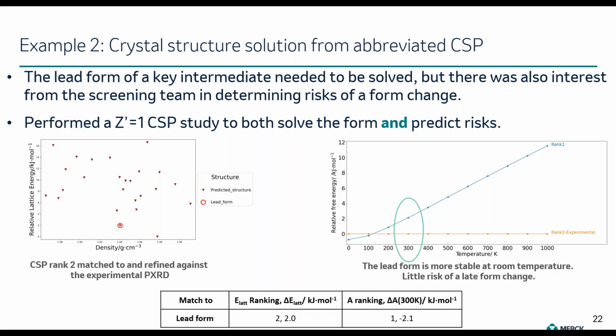And as you can see here, the stability changed quite drastically from lattice energy to free energy at room temperature. This crystal structure went from being metastable by 2 kilojoules per mole to be more stable than the lattice energy global minimum by approximately the same amount. And this is a very nice example of how in the same study, we were able both to solve a crystal structure, but also to understand its landscape, at least within a limited search space.